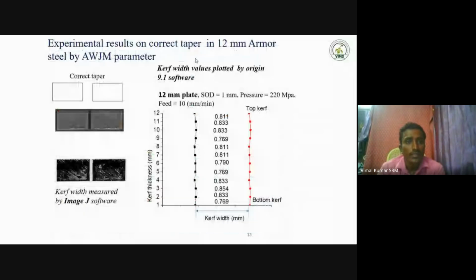So these are the experimental results of the correct taper in the 12 mm armor plate. In this condition, SOD1, pressure is 220 megapascal, feed, because I already told you that the second one is suitable for the kerf angle. For this kerf angle, I also checked with the ImageJ software to get each reading. Because this is a 12 mm plate, I can measure each gap, the center gap of the cut surface. So I will take 12 readings of the gap between the two cut surfaces.